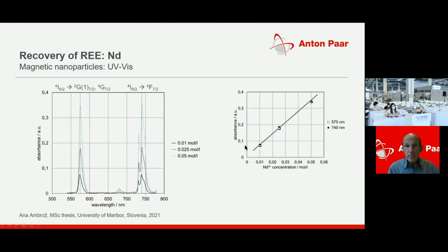Finally, we have performed some adsorption experiments by adding magnetic nanoparticles to an aqueous solution of neodymium nitrate, and we used UV-vis absorption spectroscopy to detect the depletion of neodymium in solution. We used the peaks at 575 and 740 nanometers to first establish a calibration curve that correlates absorbance to concentration of neodymium in solution.